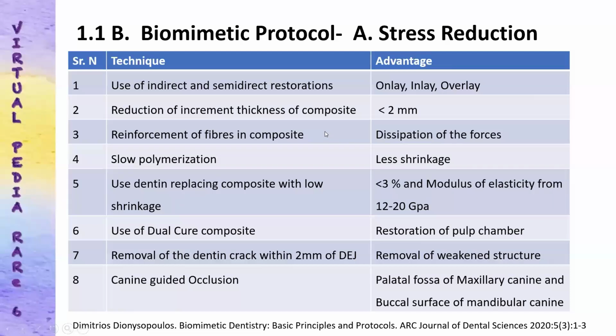If in case the thickness of the restoration is more and it is going to start from the pulp chamber, then a dual cure composite is preferred over the regular condensation composite. It is imperative to remove the dentinal crack within 2 mm of the DEJ because it is the weakest area where the stress will be concentrated and which may lead to failure of the restoration.